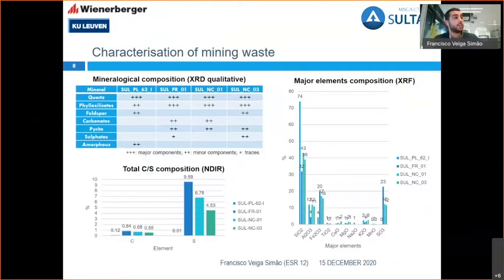A bit on the characterization of this mining waste material. Even though it's sulfidic, so you indeed have some pyrite content in some of them, the majority is composed of quartz and phyllosilicates such as muscovite or chlorite. And the pyrite is present in the Freiberg and Neves Corvo waste rock materials and the Freiberg tailing. And indeed, it goes along with the major elements composition, with high silica, alumina, and also iron oxide content, as well as sulfur trioxide. For the sulfur, we tend to look more into the total carbon and sulfur composition here at the lower left, where you can see that the last three mining waste materials, Freiberg and Neves Corvo, have higher contents in carbon and especially in sulfur.